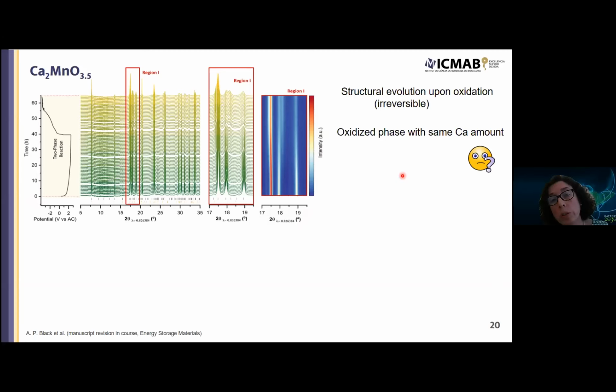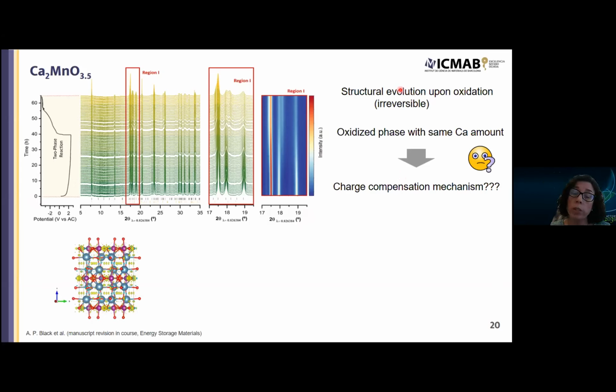The issue is that when we were trying to refine the occupation of calcium in this oxidized phase, we ended up with the same calcium amount as the pristine phase, which means that the charge compensation mechanism must be different. So if it's not extraction of calcium, it could be intercalation of anions. And in fact, when we did the Fourier map, we were able to see some electronic density in this position, which was the oxygen vacancies, which we saw before, and also on this plane in which the Ruddlesden-Popper compounds are known to intercalate fluorine. So we did some attempts to confirm whether there was fluorine intercalation. It could have been oxygen maybe as well.